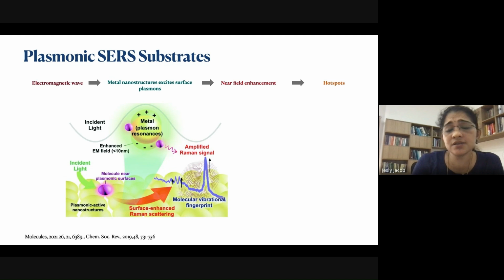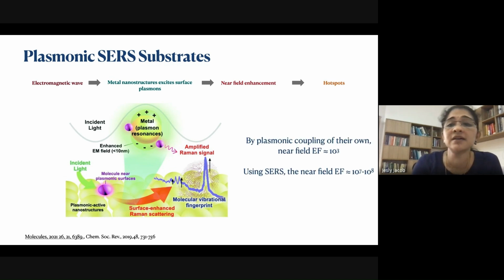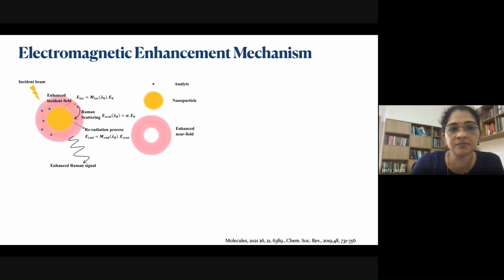So it is very advantageous, because plasmonic coupling itself has a near field enhancement factor of the order of 10³, and we are using SERS. The near field enhancement is reported up to 10⁷ or 10⁸, and we are getting more than that. What is happening in this electromagnetic enhancement mechanism? The incident beam is incident on the nanoparticle here. The nanoparticle will produce an enhanced near field around it, and the analytes around it will scatter the radiation and produce re-radiated Raman scattering. This re-radiated field will combine with the enhanced incident field, or the localized field, and an enhanced Raman signal is produced.